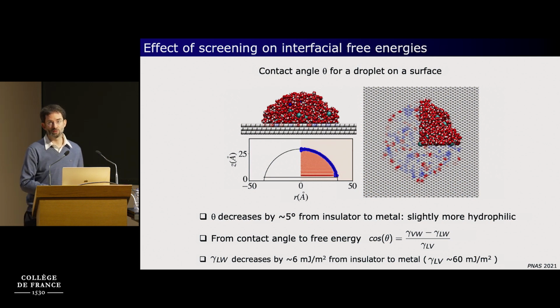In the insulating case, of course, you do not have this polarization of the metal, and this has an influence on the contact angle, which decreases by about 5 degrees from insulator to metal, which means that the metal is slightly more hydrophilic. And you can translate this change in contact angle into a change in the interfacial free energy between the liquid and the wall, thanks to the Young equation. And the associated change in the liquid-wall surface tension is a decrease by about 6 millijoules per square meter, which may not mean a lot to you, but that's a decrease when you switch from insulating to metal.